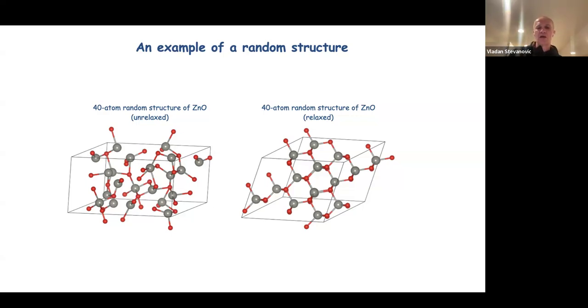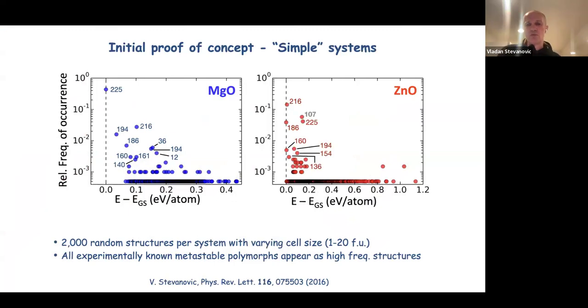Okay. So then initially, we really tested this hypothesis on just a few very simple systems. So what I'm showing you here are the results for magnesium oxide and zinc oxide. 2,000 random structures were generated for each of these. And then these plots show the relative frequency of occurrence in the random sampling of different structure types, different local minima, as a function of energy on the x-axis. The numbers here represent the international space group numbers.